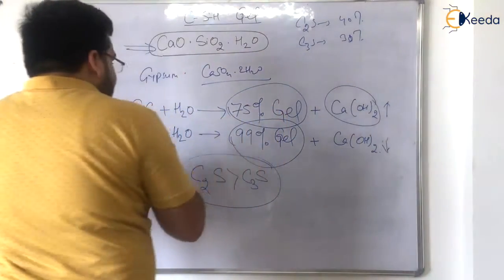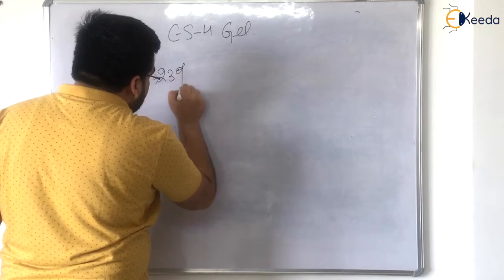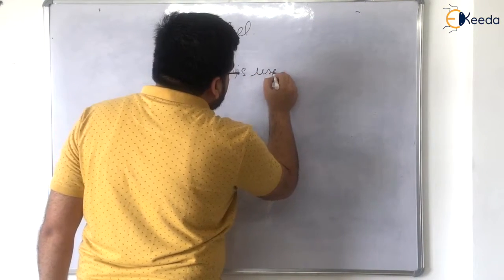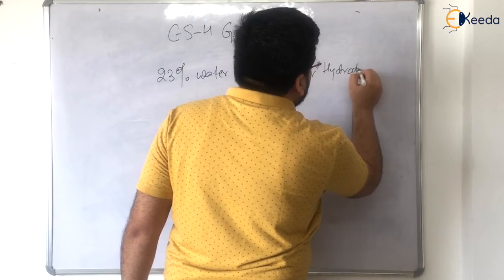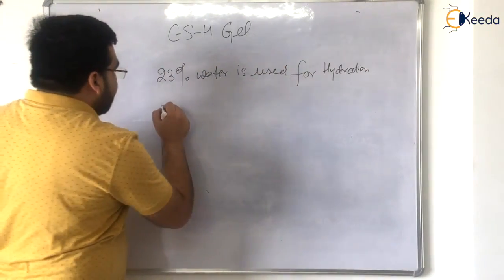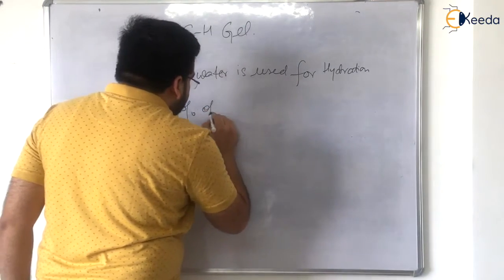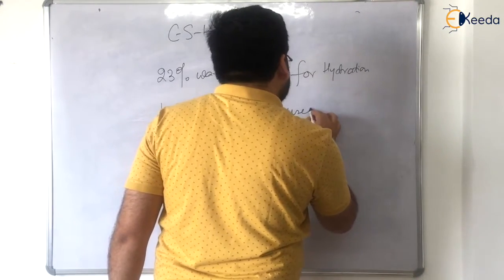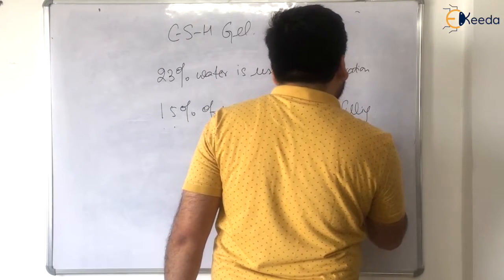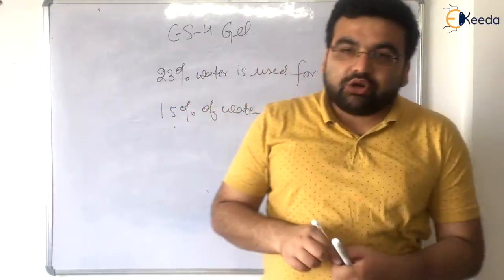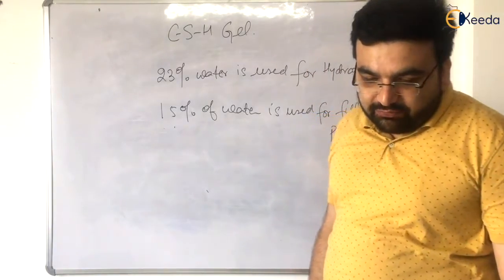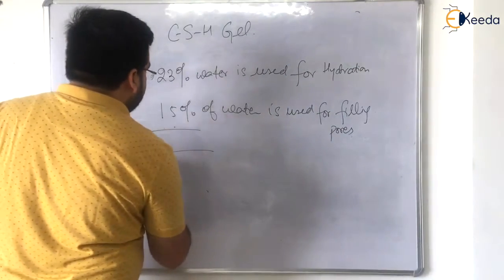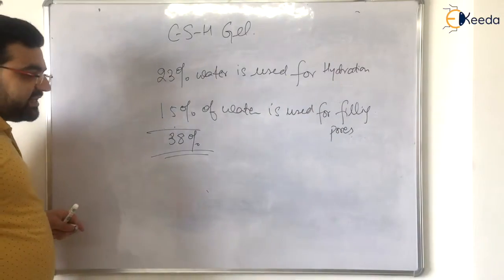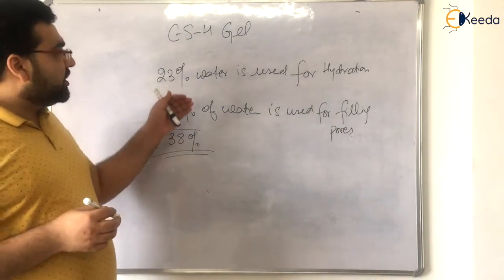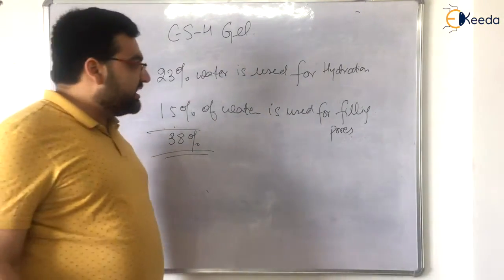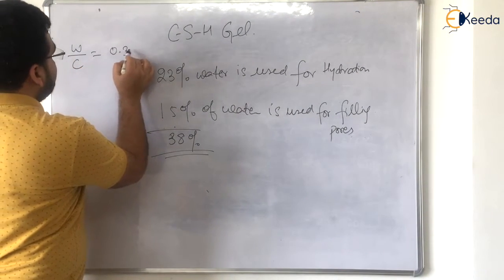The percentage is, let me write it: 23% of water is used for hydration and around 15% of water is used for filling pores. So this is important, that around 23% of water is used for hydration and 15% is used for filling the pores. So in total it comes to around 38%. If somebody asks what is the percentage of water used in cement, you will say around 38% of water. So the water cement ratio will be around 0.38.